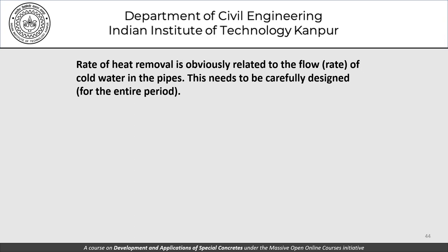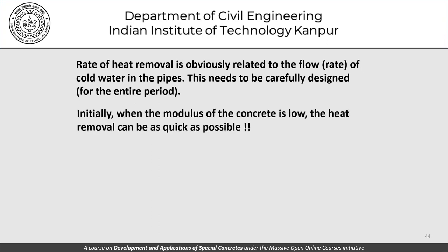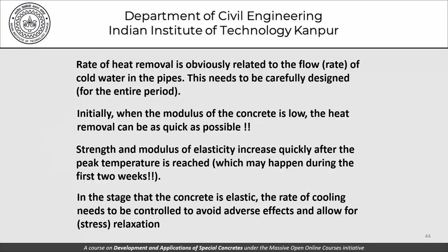The key question in post-cooling is when to start water circulation and at what rate. The rate of heat removal relates to the flow rate of cold water. Initially, when the modulus of concrete is low, heat removal can be rapid. Once the concrete enters the elastic stage — as strength and modulus increase quickly after the peak temperature, typically within the first one to two weeks — the rate of cooling must be controlled to avoid adverse effects and allow for relaxation.